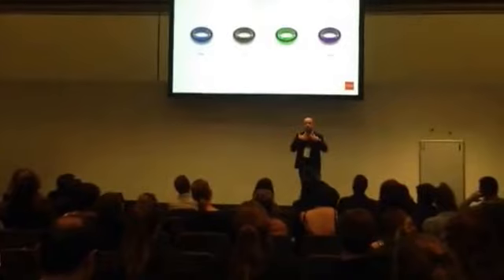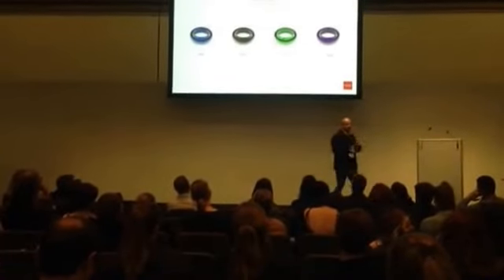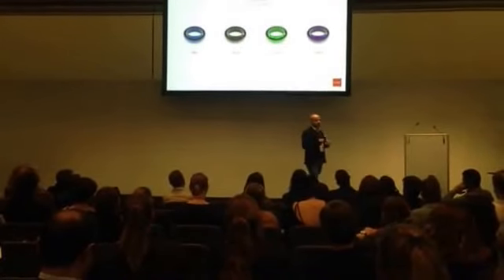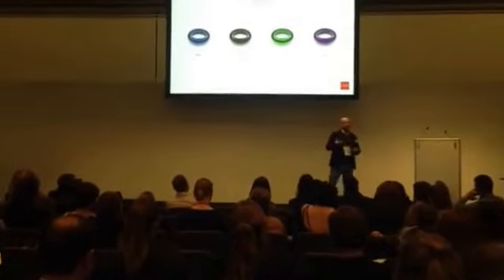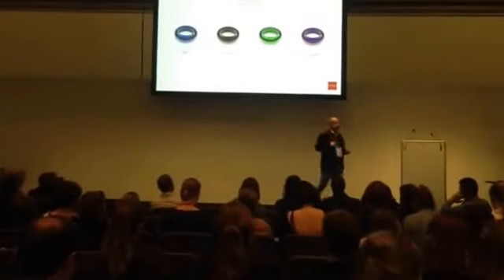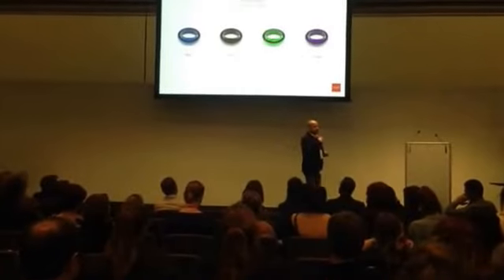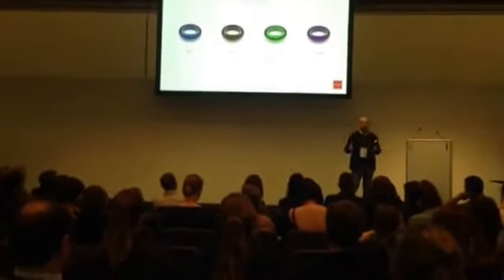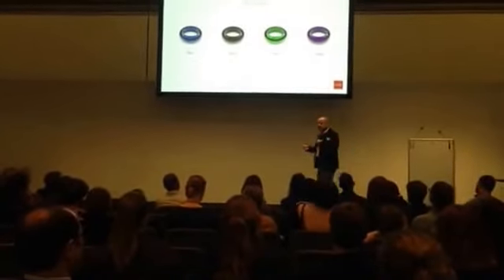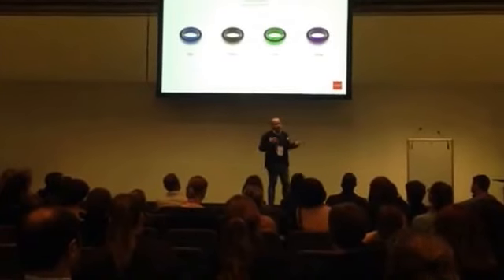And then titanium gives another opportunity, anodization, the possibility to produce jewelry and then do a galvanic-like process. I mean, there is no deposition, it's an oxidation on the surface, and you can get many colors, and the colors depend on the thickness of the titanium oxide layer we have on the surface. I will say that the thickness of that layer is typically like the rhodium plating that we have in jewelry, which is something like 200, 300, 400 nanometers. So it's also very long-lasting.